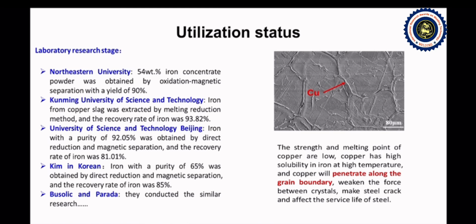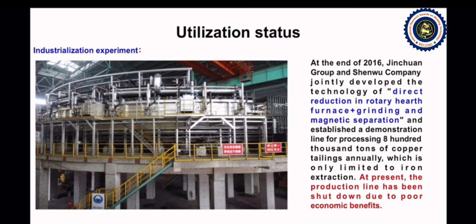That is because the strength and melting point of copper are low. Copper has high solubility in iron at high temperature, and copper will penetrate along the grain boundary, weaken the force between crystals, make steel crack, and affect the service life of the steel. At the end of 2016, Jinchuan Group and Shenwu Company jointly developed the technology of direct reduction in rotary hearth furnace, grinding and magnetic separation, and established a demonstration line for processing 800,000 tons of copper tailings annually, which is only limited to iron extraction. At present, the production line has been shut down due to poor economic benefits.